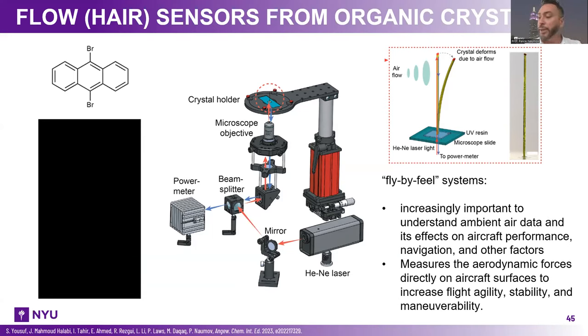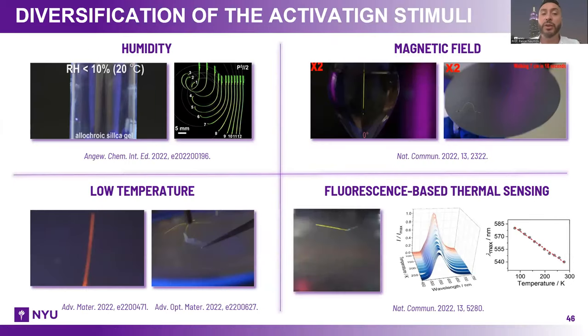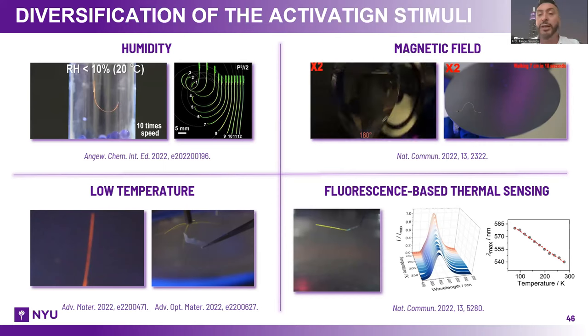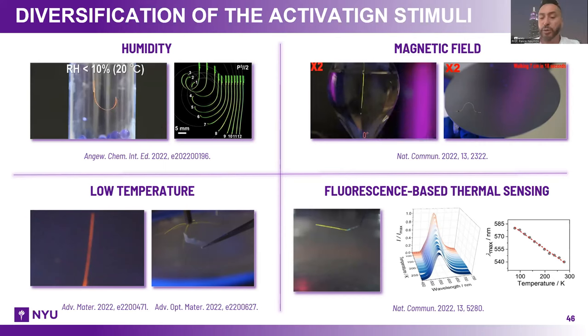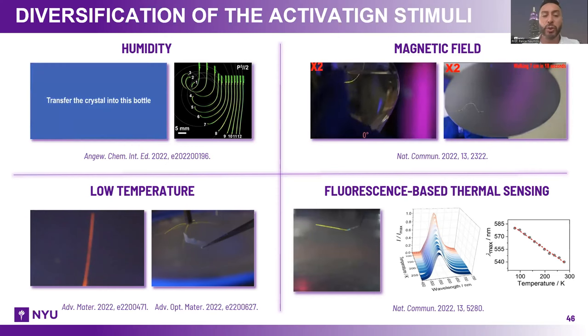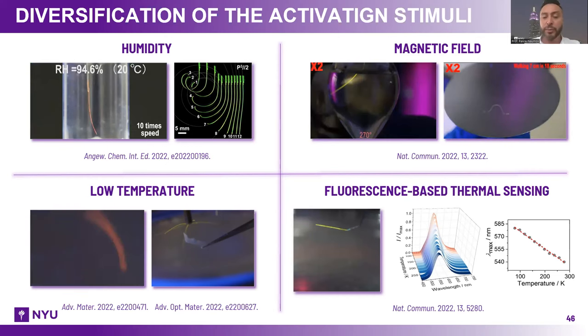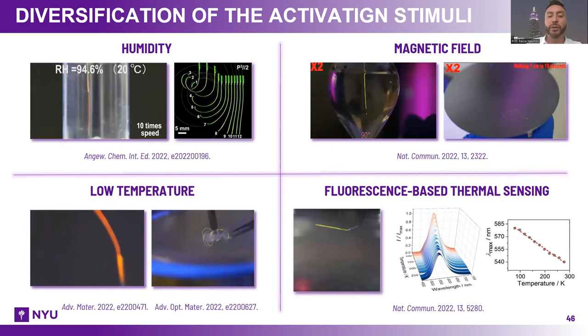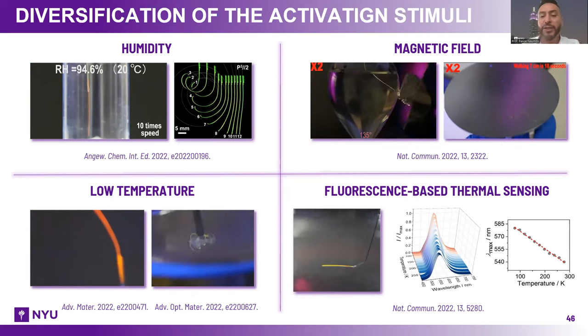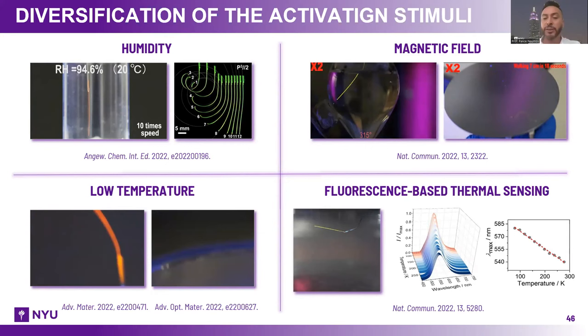Our other exploration directions are to diversify the number of stimuli that we can use to affect the crystals. We have explored the layer-by-layer approach, where we deposit polymers on the surface of crystals to control their shape by humidity, magnetic fields, in water and other liquid environments, which can be important for underwater applications. We can use low temperature to make soft robots that can grip objects, release load, and transfer load from one place to another. We can also use the strong dependence of the fluorescence of some of these crystals to measure temperature. So we can monitor how fluorescence changes and use that change to measure temperature in the crystal environment. And you can see all of these materials here are hybrid materials.